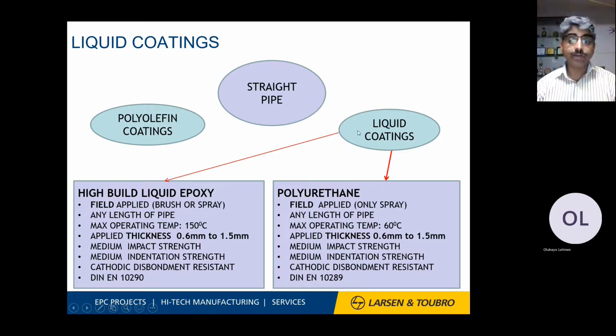The other coating is called liquid coating, which is applied with the pigments, as we saw before. It is always a field coating, applied with the help of brush or spray, or you can apply it only by spray if it is polyurethane. If it is a high build liquid epoxy, which has higher DFT, that can be applied with the help of brush and spray at shop and site. Normally the site uses this technique more because it is easy to apply over any elevations.